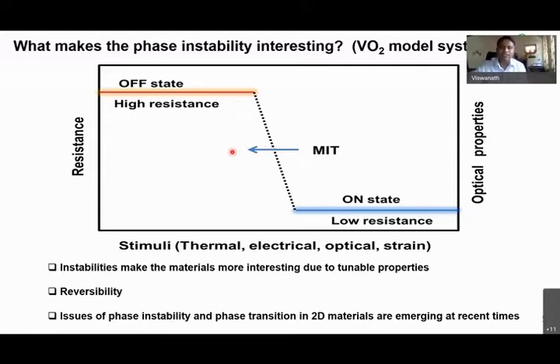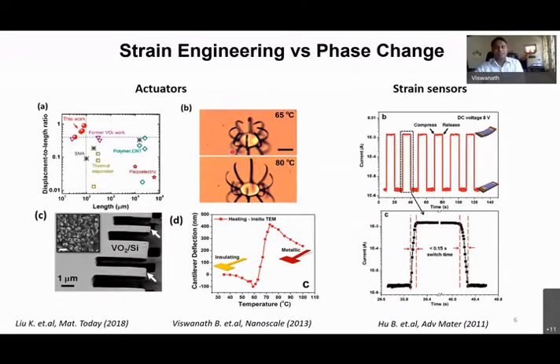And also some of these phase transformations are known to be stable, in the sense that up to 10 power 6 to 8 cycles, we can reversibly tune their properties. And the time scale is another interesting aspect. Some of these phase transformations are found to be typically at least nanoseconds. There are also studies showing that even at picoseconds, the transport properties can be manipulated, but there is a structural relaxation that follows the electrical properties. That way, at least hundreds of nanoseconds is really a fast phase transformation we can reversibly use.